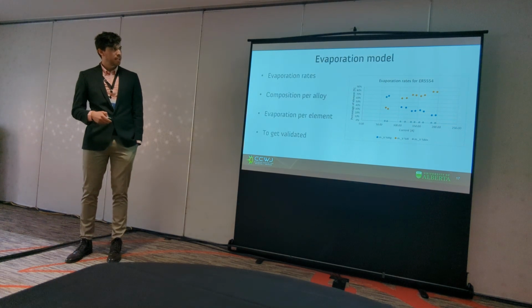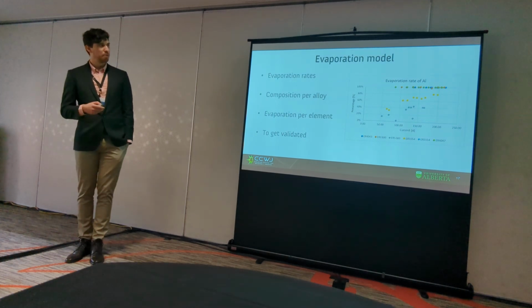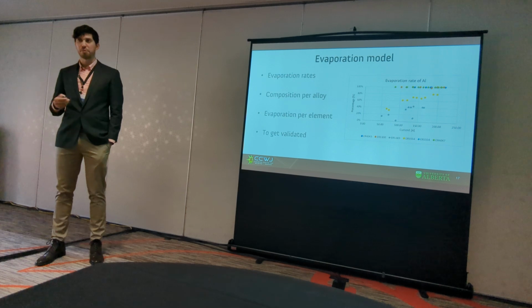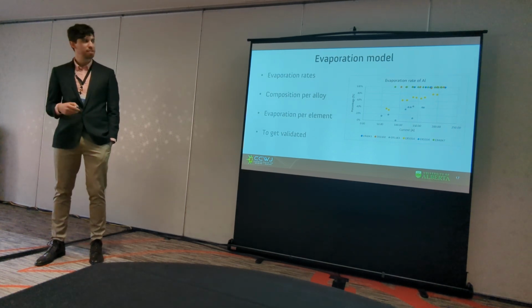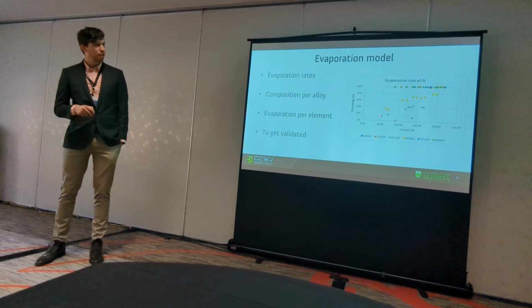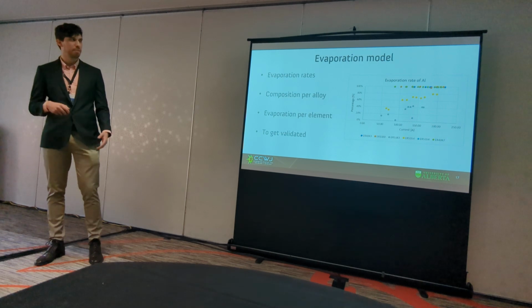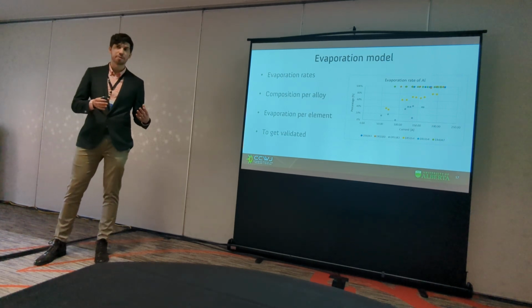Also, we can say by element how aluminum is going to evaporate. Well, most of it is going to stay 100% because it's the main component of these alloys. But in other ones, we're going to see that just 20% of the entire composition of the vapors is going to be aluminum, and in the real composition, it's about 90-something% aluminum.